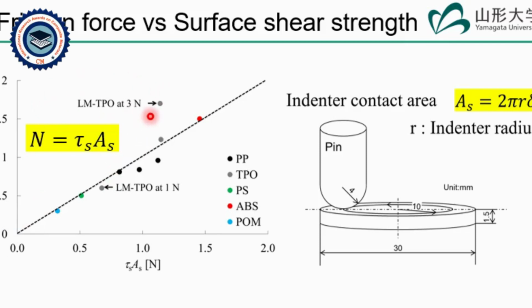had a calculated value lower than the experimental value, because LMTPO was the softest material used for this study, and therefore the indentation depth was greater than for the other materials. It's possible that deformation attributable to loading might have reached the bulk region. For confirmation, a 1 Newton pin-on-disk test with LM-TPO was performed. The result is shown here.